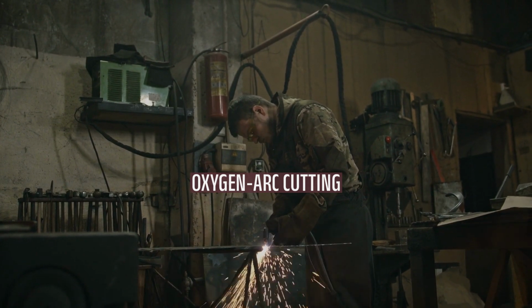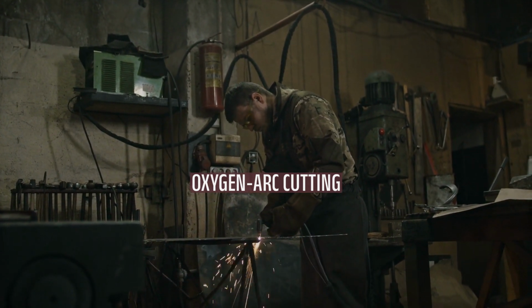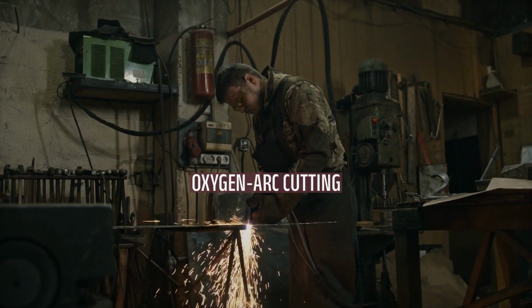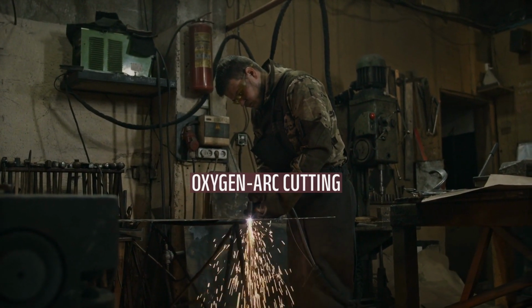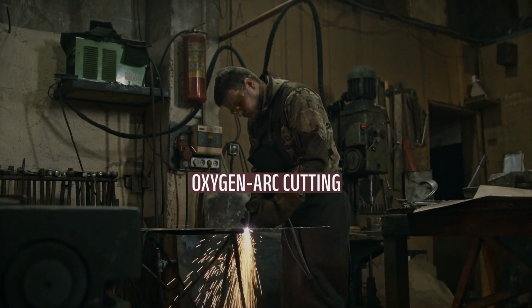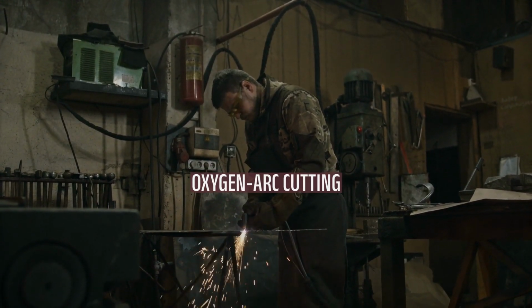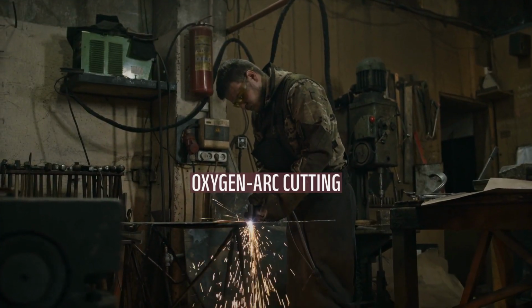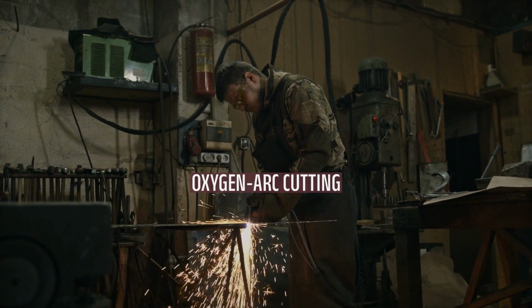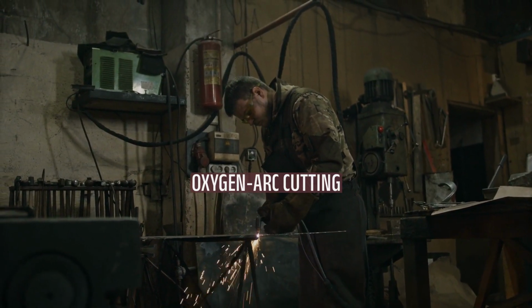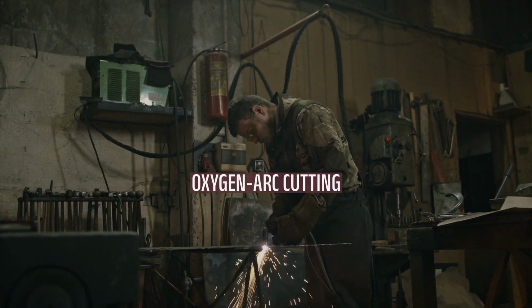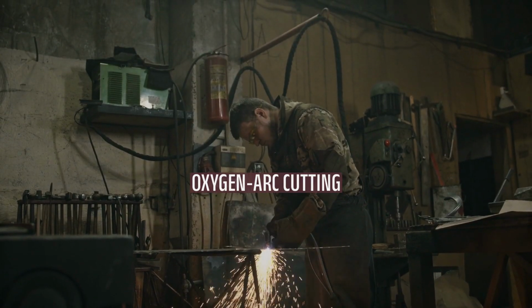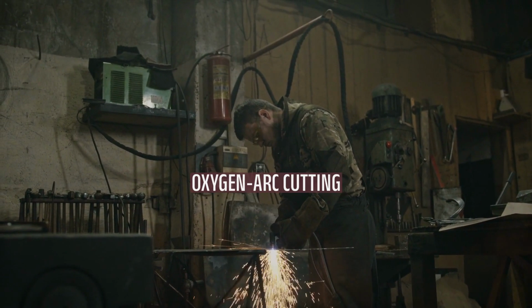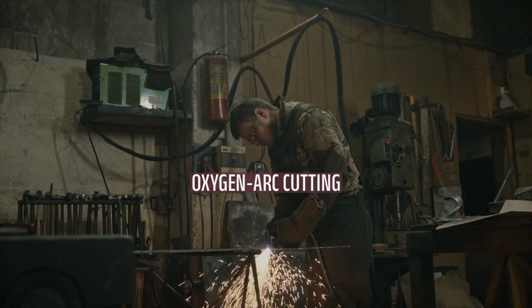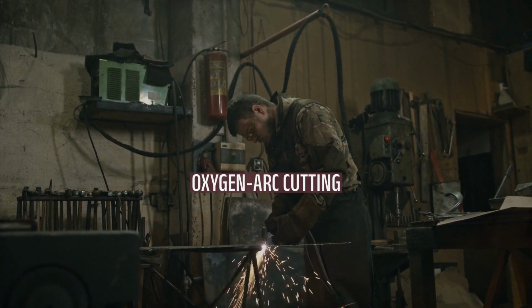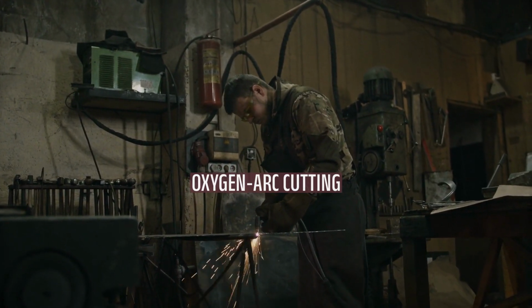It can use steel tubular electrodes or exothermic electrodes, which continue to burn independently of the arc once ignited and the oxygen is flowing. Oxygen arc is preferred where practicable because it cuts plain and low-carbon steel well. It is usually used with a constant current DC welding generator set on straight polarity, and the arc should ignite as the electrode touches the work.